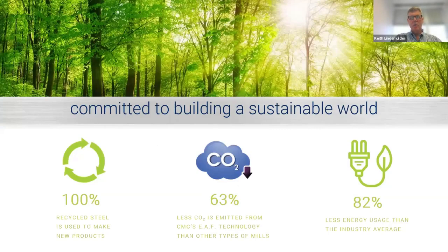In the steel industry, one major difference is how steel is produced. High recycled content not only reroutes end-of-life steel scrap out of landfills and into new steel products, it avoids much of the emissions generally associated with the processing of virgin iron. Every ton of steel that is recycled conserves 2,500 pounds of iron ore, 1,400 pounds of coal, and 1,200 pounds of limestone. By using a scrap-based EAF steelmaking process, our CO2 emissions are more than 60% less than the global